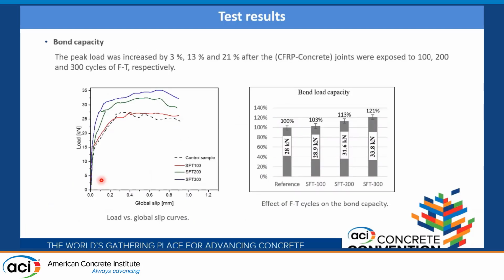The left figure presents the load versus global slip curves, which were obtained from the LVDT recording data. And the right figure shows that the bond capacity of CFRP concrete joints was increased by 3%, 13%, and 21% after 100, 200, 300 freeze-thaw cycles respectively.